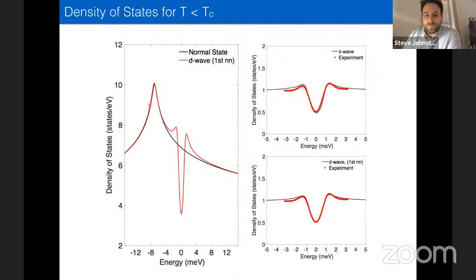We have this Van Hove singularity which complicates matters. And so the way we're going to eliminate it is the standard trick of dividing the superconducting and the normal state densities of states and comparing that. We'll do the same for the theory and the experiment. And when we do that, we get the dots that are shown here. What we found is that we can basically fit this with whatever order parameter we feel like putting in. So we put in d+id, we put in s, whatever we put in, it produces about the same level of fit. The reason for that is there's a broadening parameter, this Dynes broadening parameter, that ends up being pretty large. And that completely obscures all of the structure that's happening down here.